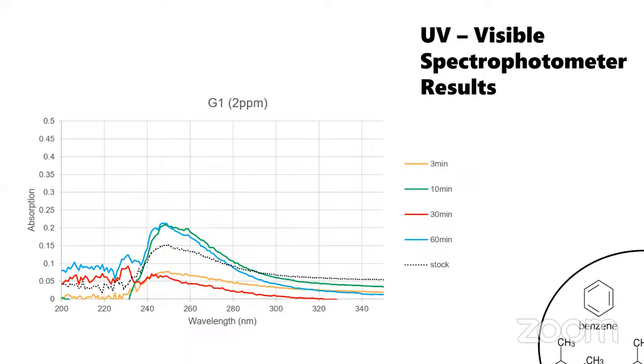To see the effect of this photocatalyst during the testing period, samples were taken at certain time intervals and tested using UV-Vis, which gives the absorption as a function of the wavelength. Next slide, we can see that in the first 30 minutes, there was a complete degradation of the BTX, followed by a slight increase as time progresses.